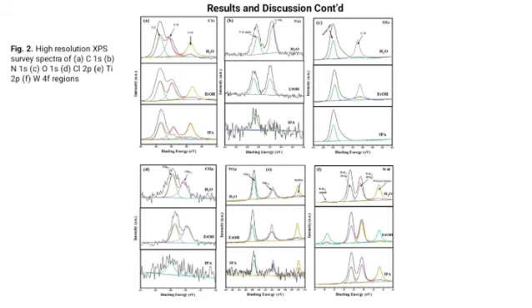Meanwhile, the deconvoluted carbon 1S spectra showed three prominent peaks at 284, 285, and 288 electron volts, which could be attributed to the C single bond C, C single bond O, and C double bond O bonds, respectively. In the same vein, the nitrogen 1S revealed an intense peak at 399 electron volts and 402 electron volts, which are ascribed to the organic nitrogen bond of an amide and the C bonded to an amide group, respectively. While the oxygen 1S spectra revealed two peaks in the water and the ethanol-based material and a single peak in the isopropyl alcohol-based material.